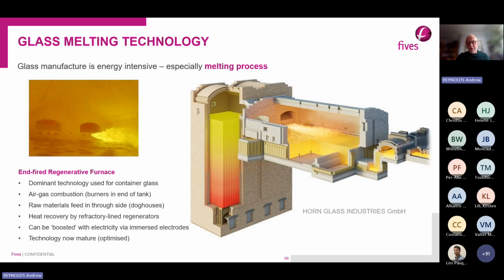Glass manufacture is a very energy-intensive industry. Especially the melting process. It's necessary to melt raw materials at very high temperatures. We're talking here in the order of between 1350 and 1500 degrees, depending on what sort of glass we're talking about. We do recycle glass into the process. We call it cullet. And furnaces can use anything between very low levels of cullet, 5%, 10%, up to very high levels of cullet. In terms of bottle production, it can be as high as 70, 80% cullet. But it doesn't really change the fundamental process in that we're using gas really to heat the materials.